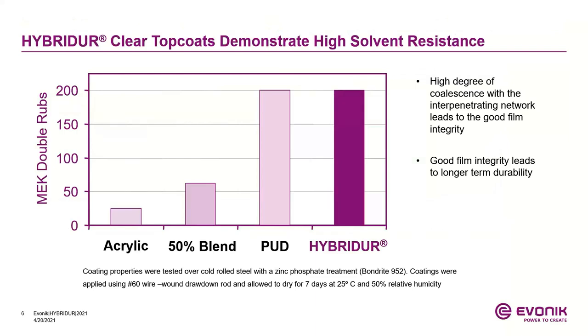So we further demonstrate this aspect by measuring the MEK double rubs of an acrylic, a 50% blend of an acrylic and a polyurethane dispersion, the polyurethane dispersion itself, and the Hybridurs. We tested the coating properties over cold rolled steel with a zinc phosphate treatment. The clear coatings were applied using a number 60 wire wound rod and allowed to dry for 7 days at 25 degrees and at 50% humidity. MEK double rubs tests were then conducted.